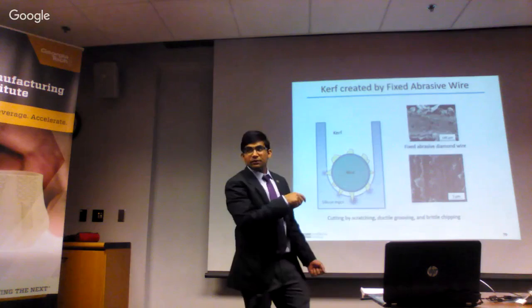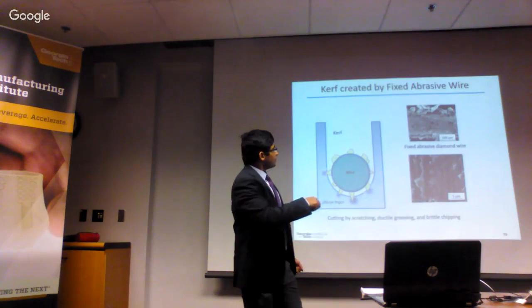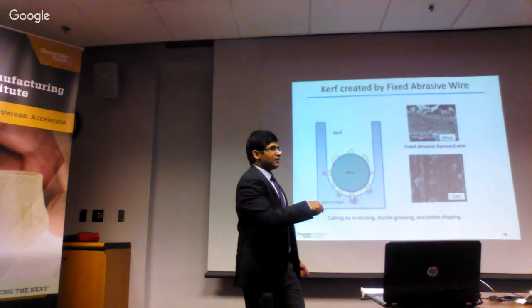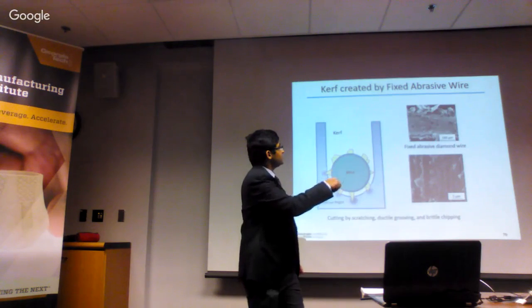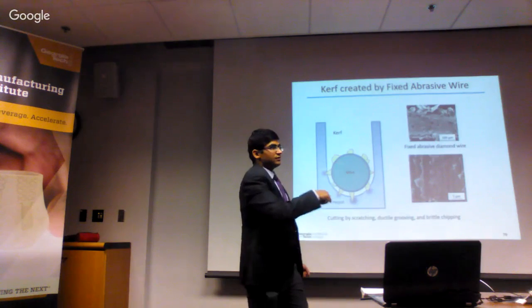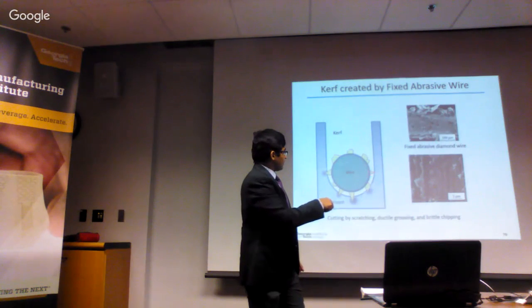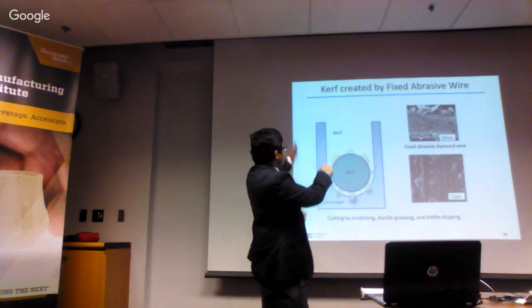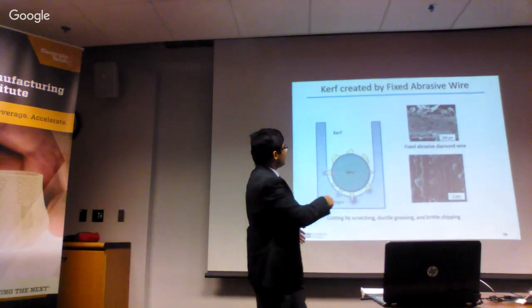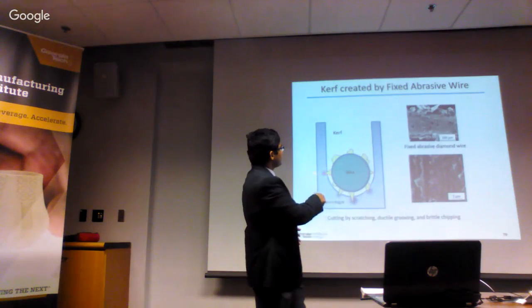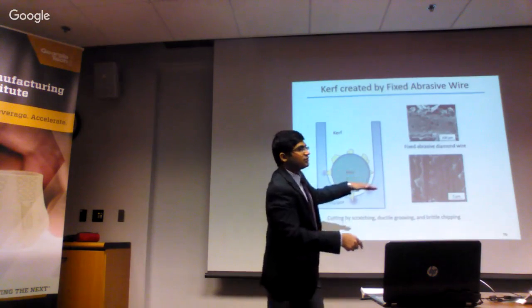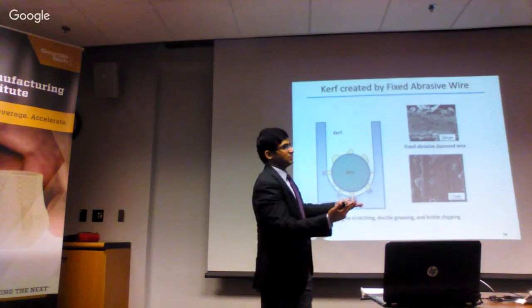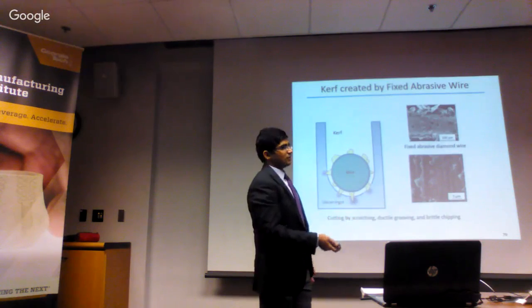Yeah, go ahead. So whenever an abrasive is contacting silicon, what we are seeing here is the sidewalls of the kerf. And let's see this abrasive, right? It creates median cracks as well as lateral cracks. The lateral cracks are chipping out. So if this becomes a wafer like this, the lateral cracks are chipping out, and the median cracks are perpendicular to the wall. So when you take a section, if you get to the deeper trenches, you're putting median cracks into the wall.